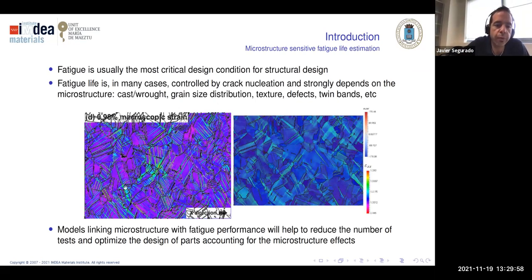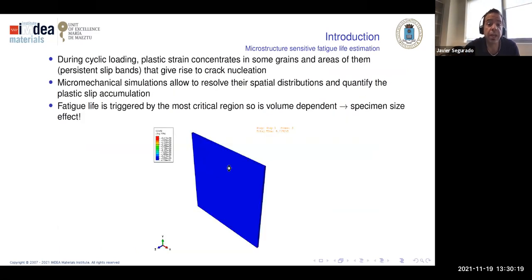How? Well, we form somehow localization of strain. Here is an experiment. Here is an FFT simulation. You can see how when we have a twin band, for example, deformation localizes there, and this localization cycle by cycle starts to degrade the material and somehow nucleates a crack. Okay, so we need models that take this into account.